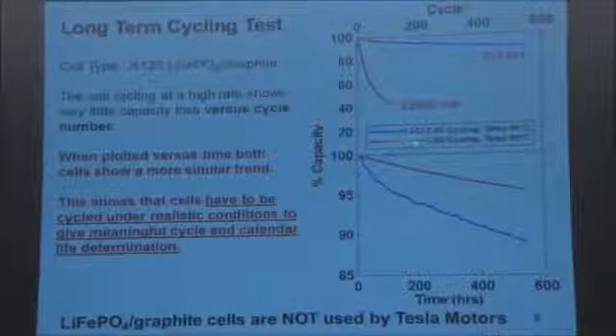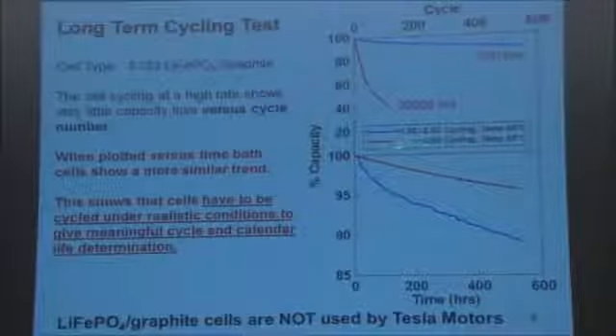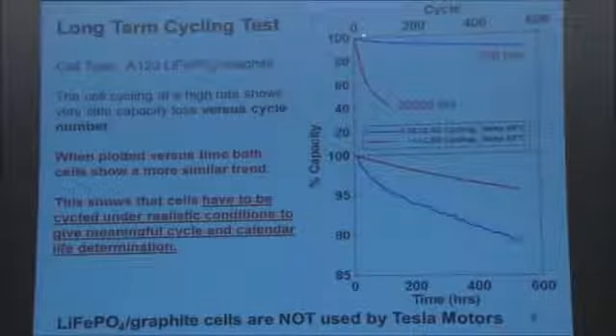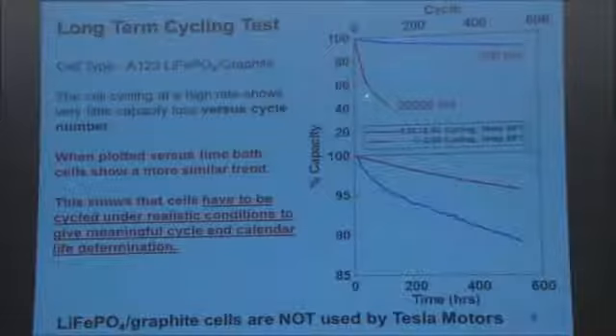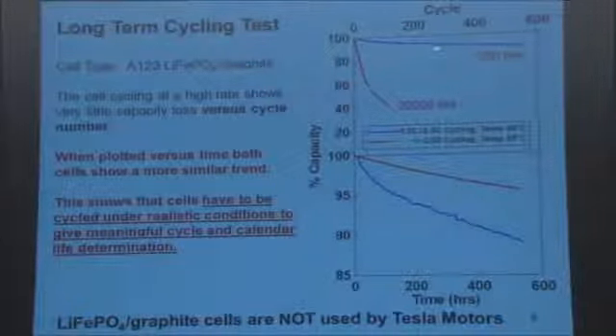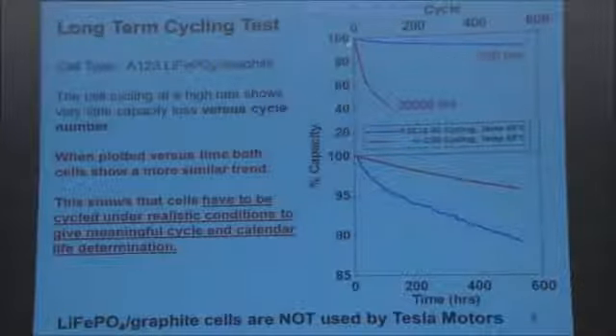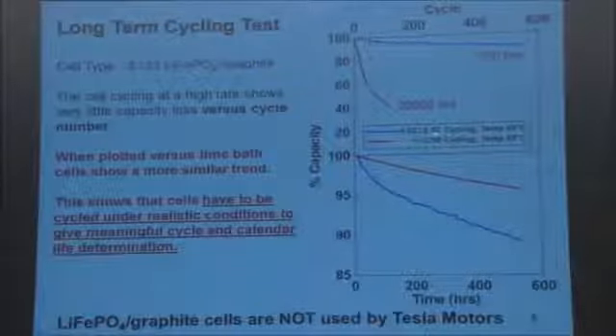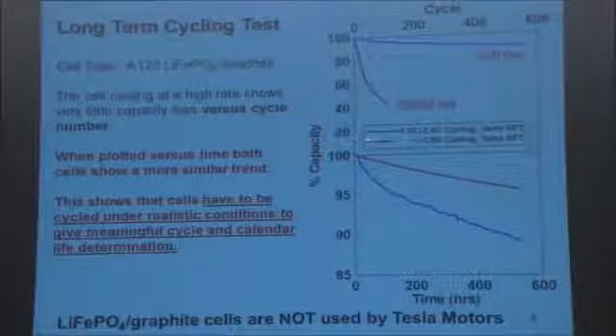Now, if you take the same exact cell, which comes from A123, and you test it where the discharge takes 56 hours and the charge takes 56 hours, it's the red curve. And you plot capacity versus cycle number. You can see the thing dies really fast in cycle count. So this blue data is the 60-degree data I showed you on the previous slide. And the red data is what happens if you go much more slowly. So the time of each cycle takes much, much longer.